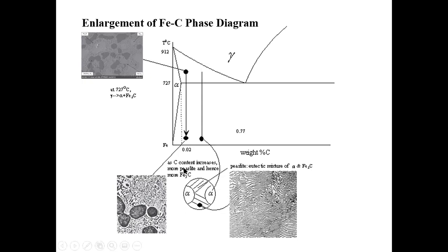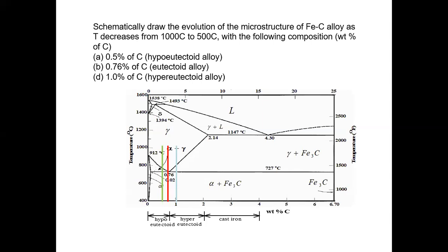But there's another terminology that I want to quickly talk about. People typically call this stripe-like eutectoid microstructure, composed of both iron carbide and the alpha phase, pearlite. It's the eutectoid mixture of alpha phase and iron carbide. So that's pretty much all I want to say about this phase diagram. You can also do some calculation, as I said before, in a very similar fashion to what we described for the eutectic transformation. The key is just to identify the correct composition to use and apply the correct lever rule. I will skip that for the sake of time.